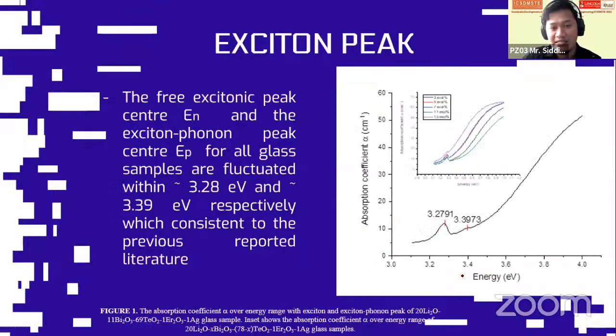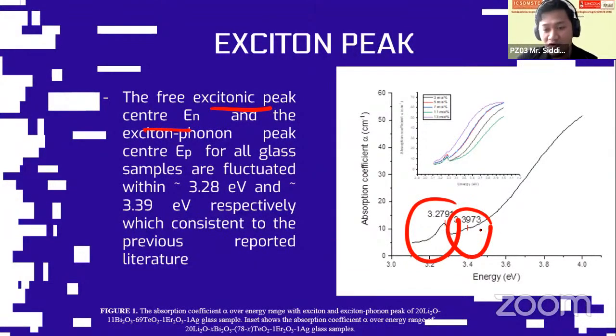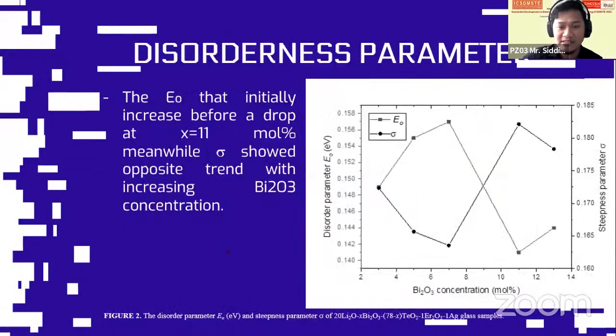So the result and discussion. From our discussion, we can see this is my optical absorption data. We can see two peaks here. Actually, if we reconvolute, we can get two peaks. The first peak here actually comes from the free excitonic peak center, so it indicates the exciton formation. And then this is the exciton-phonon coupling peak. From our research, we can get the same energy, consistent also with the previously reported literature.